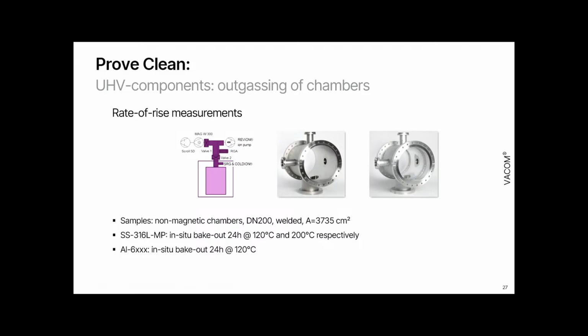Then a different way of doing it is a so-called rate of rise measurement. We've used these for validating our aluminum chambers that we produce, our CF aluminum chambers. So basically, this is even simpler. You have your chamber, you pump it down, you close off the pump, and you just let the chamber sit there and measure the pressure increase as it's outgassing.